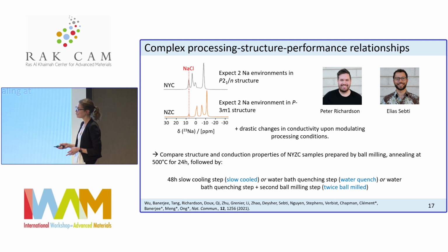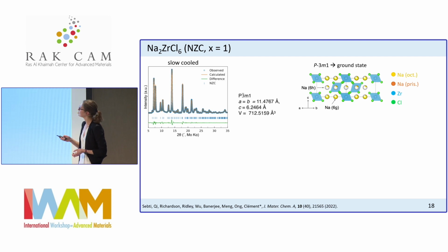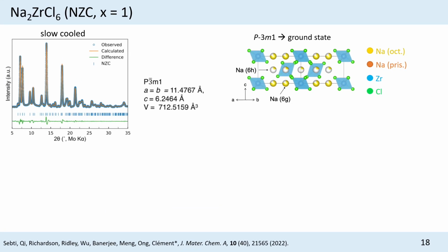One of them was slow cooling after the annealing step, so this is what we call the slow cooled sample, or we used a water bath quench, this is the water quench sample, or we used a water bath quench followed by a second ball milling step, and we call this the twice ball milled sample. And so if we start with the zirconium end-member, what we find here is that if we slow cool the material, we get a nice phase pure and monophasic material with a P bar 3M1 structure, which is what we had found in the previous study.